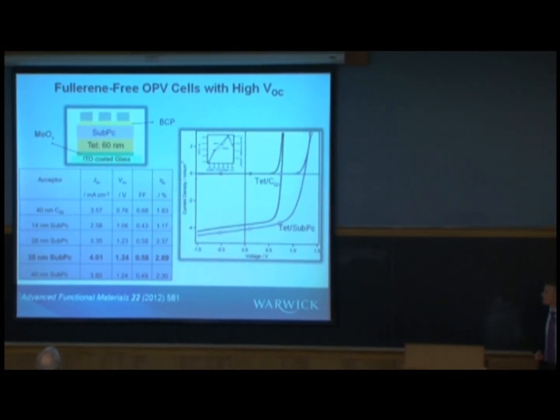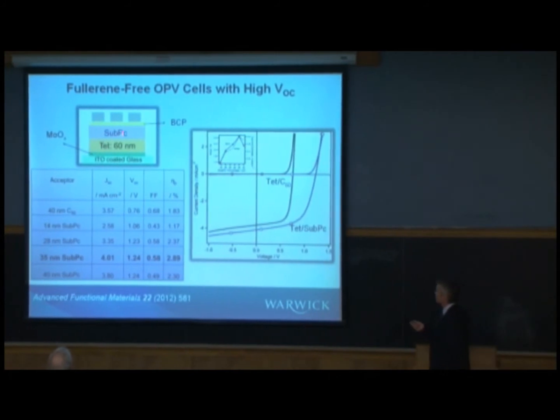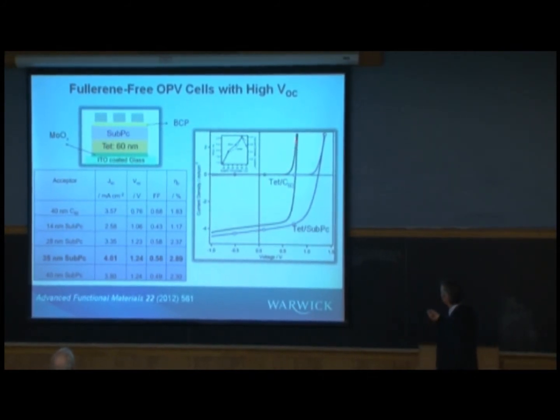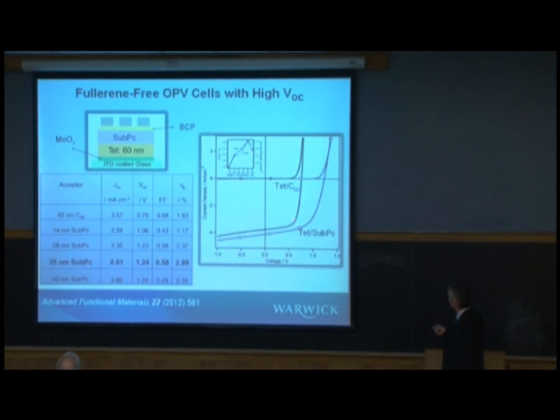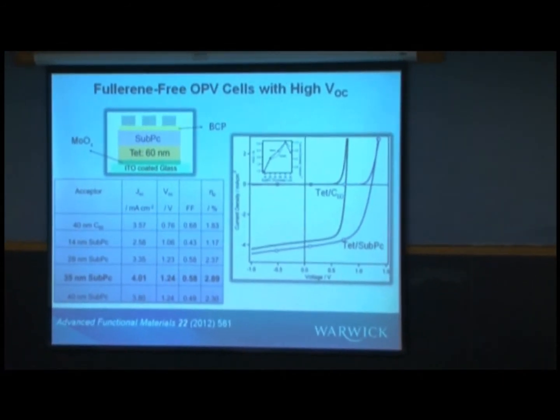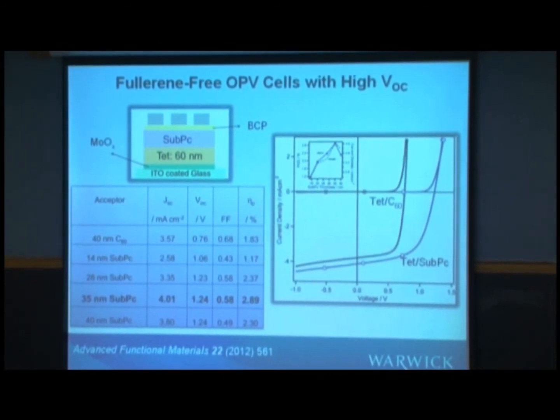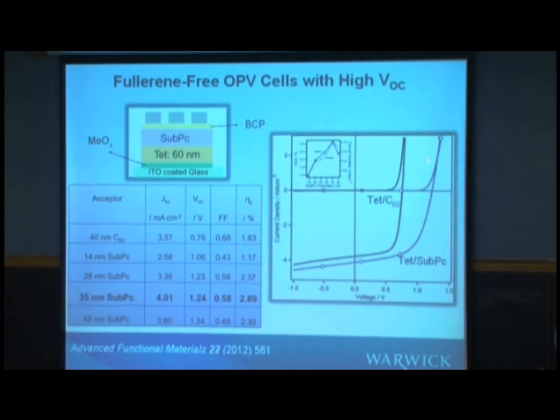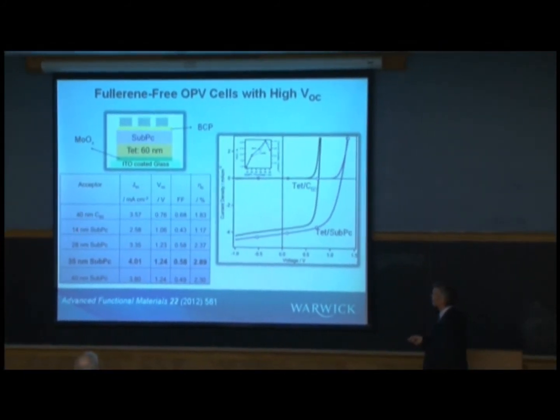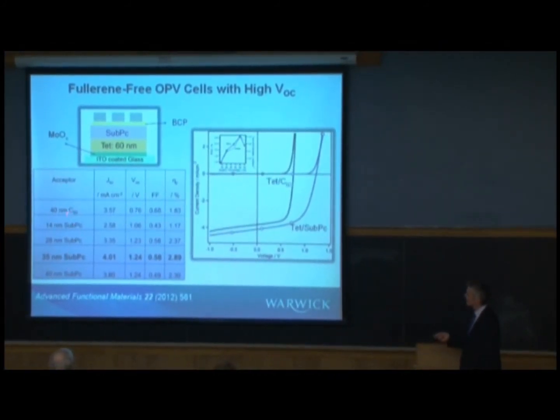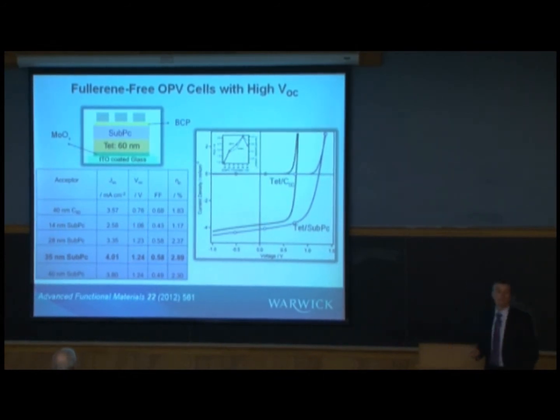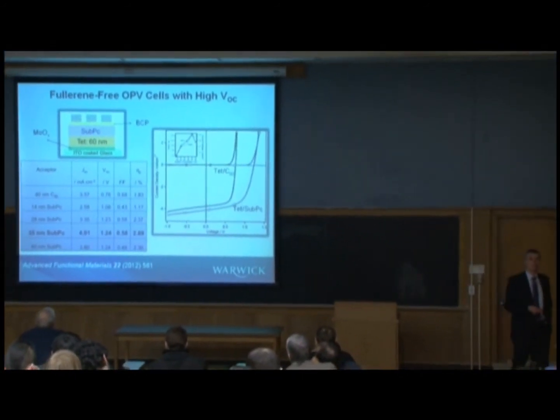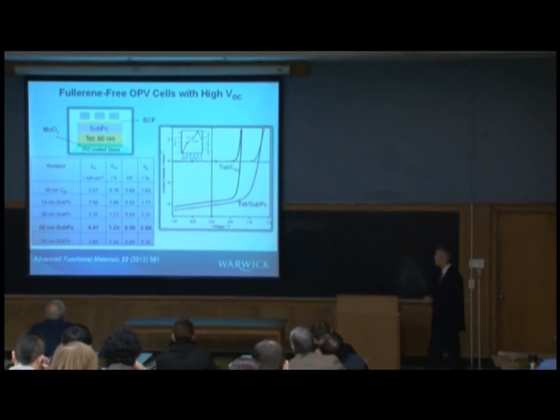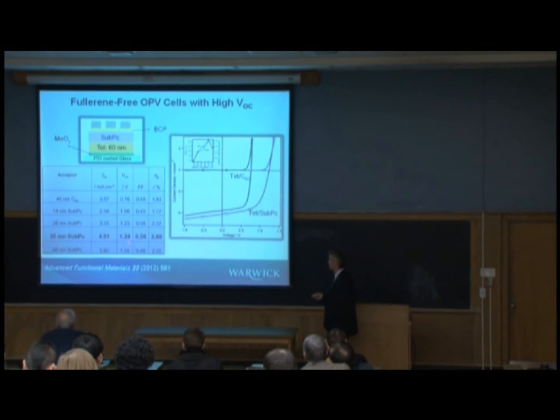So those are the current voltage characteristics for tetrazine subphthalocyanine cells. So tetrazine C60 here gives a voltage of 0.76 volts. So it's limited by that relatively low interface gap energy. But if we replace the C60 with subphthalocyanine, we get a much higher voltage. So we're now up at around 1 volt for a 14 nanometer layer. But if we increase the thickness of the subphthalocyanine layer, that goes up to 1.24 volts, which is now a pretty high voltage for an organic solar cell. And the performance overall increases because of that increase in voltage.